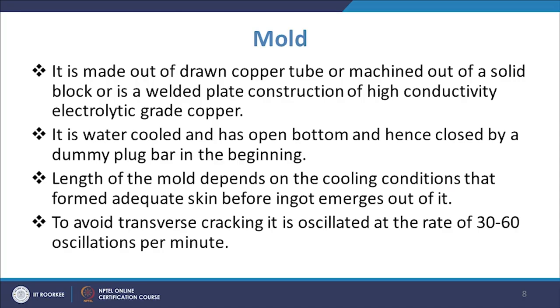So, the metal comes towards the mold. Now, we have already discussed that this mold is made of the drawn copper tube or machined out of a solid block or is a welded plate construction of high conductivity electrolytic grade copper. So, the mold in the case of continuous casting is made with high grade electrolytic grade copper, and copper is chosen for the obvious reason that it has very high conductivity and it can remove the heat of the molten metal very fast.